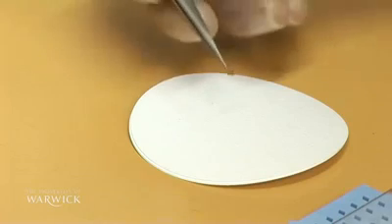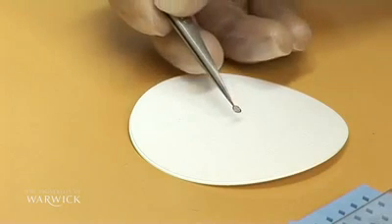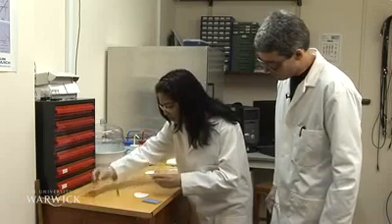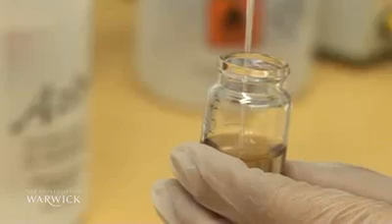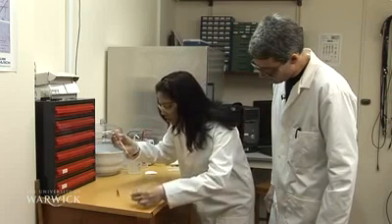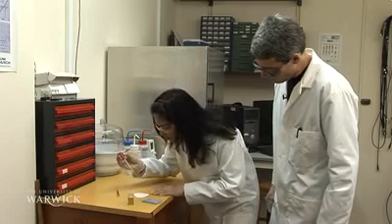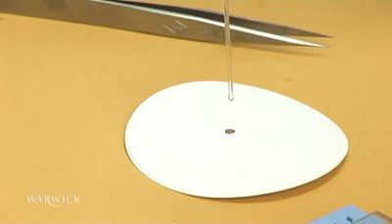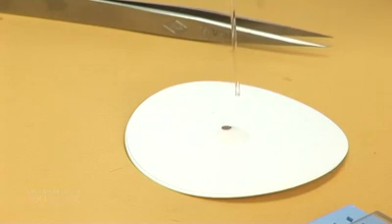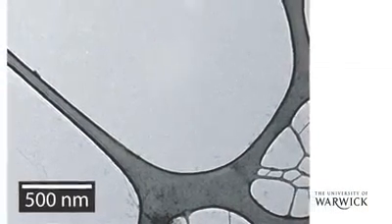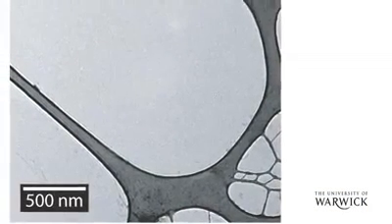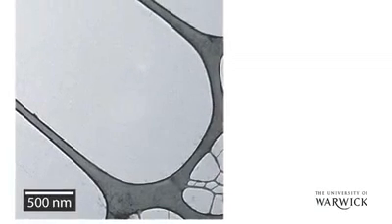TEM samples were then made by dropping a drop of graphene oxide or reduced graphene oxide solution on top of a lacy carbon TEM grid. This produces a good coverage of graphene oxide, much of which is single layer. When we look at these samples in TEM, we find that graphene oxide is nearly transparent and is robust to the electron beam.